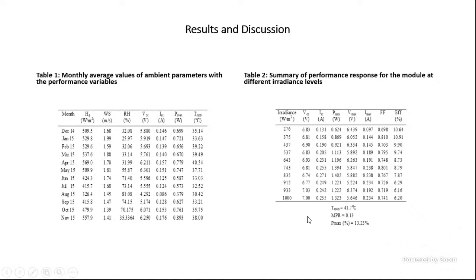And again, looking at the bottom of this table 2, at 1,000 watts per meter squared irradiance, which the manufacturers usually use to rate the module, you can see that the module temperature is not 25 degrees, as manufacturers will normally state as standard condition. Here, you can see that the module temperature at this 1,000 watts per meter squared is 41.7 degrees centigrade, which invariably will affect negatively the performance of this module at that particular temperature.